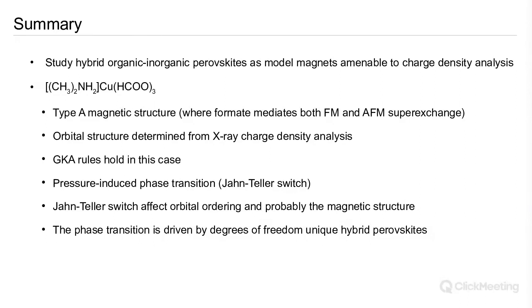We determined the orbital structure of the transition metals from charge density analysis, and we've found that the GKA rules do indeed hold in this case. We've discovered a pressure-induced phase transition, which is, if you like, characterized by a Jahn-Teller switch, and we make predictions then about the nature of orbital ordering and the magnetic structure.